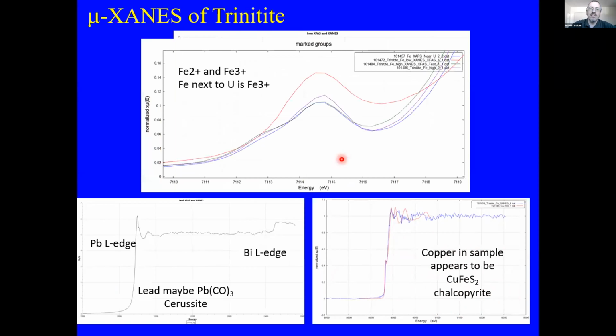But the iron edge looks quite interesting. So if we zoom into the pre-edge features, it seems to be iron-2 and iron-3. And this fits with some of the coarse data that was done beforehand, where people just ground up trinitite and looked at the oxidation states, which were non-binary. So the iron-3 is actually only seen in the samples that are next to the uranium.